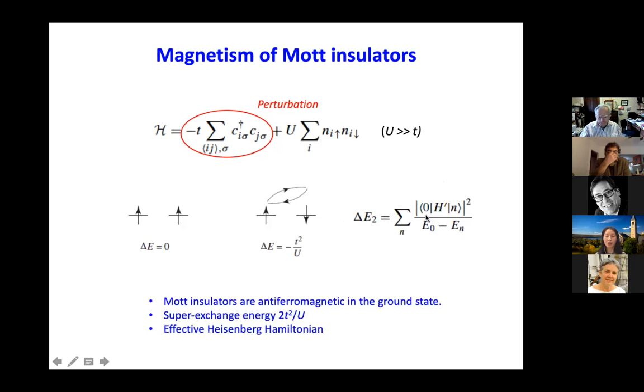And this value, you can estimate it's proportional to T squared over U, and based on all the experimental values we extracted from those measurements, this is fully consistent. And we also know that our system is in the large U over T limit. It's on the order of 20. So I'm not going to get into the details. You can look up those detailed measurements and how we map out the entire phase diagram.